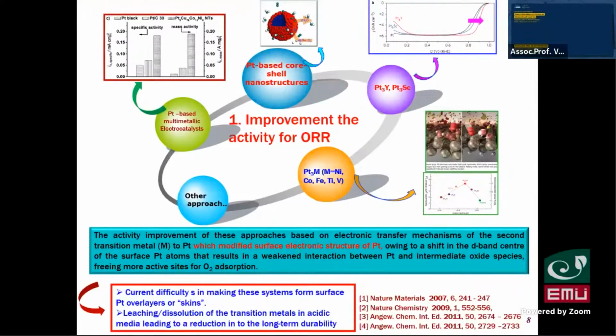So the first step, they enhance the ORR reaction by using alloys with platinum. That means they add a second metal, like PT-nickel, PT-cobalt, or iron with platinum. This way can enhance the ORR reaction and also reduce the cost of platinum.